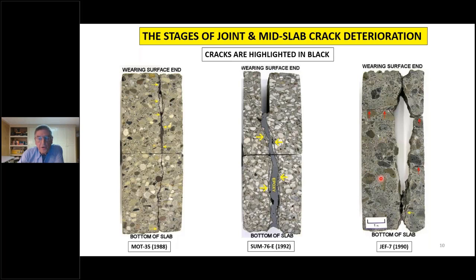And then over on the right, you have the situation where the entire center portion is now missing. This was State Route 7, Jefferson County, about 1990. And now you have, with the loss of support, the traffic-induced faulting and cracking at the top of the slab as well. So those are pretty much the sort of things that are happening. But it's the same phenomenon going on. It's just in different stages of progression.